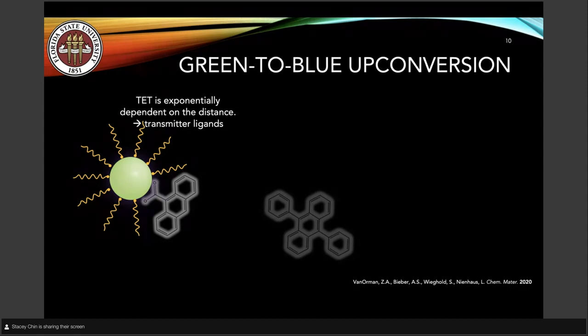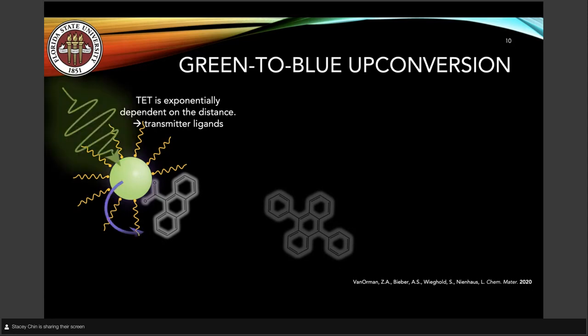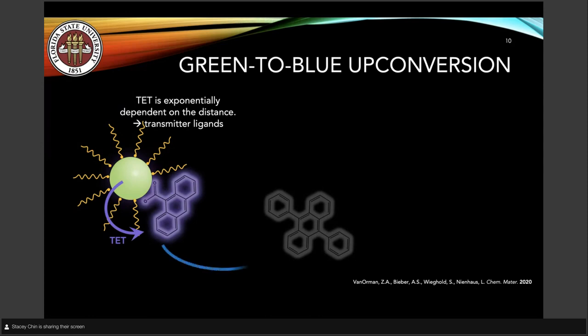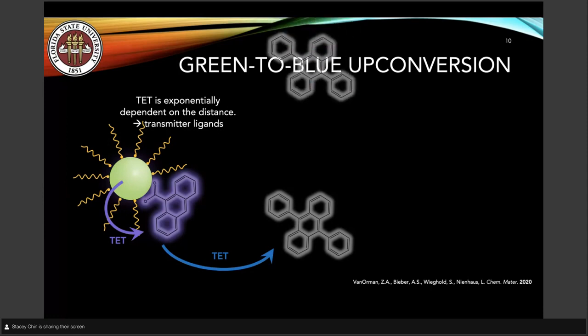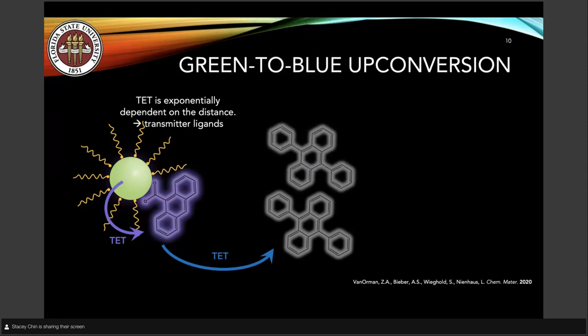So with that, we use transmitter ligands instead of doing the triplet transfer directly from our quantum dot to whatever upconversion material we're using. In this case, it would be diphenylanthracene. So it's an energy transfer cascade where you go first to this transmitter ligand, and then you create the triplet state on our diphenylanthracene. And since we're doing this in solution, if another excited diphenylanthracene collides with this molecule, you can get upconversion.